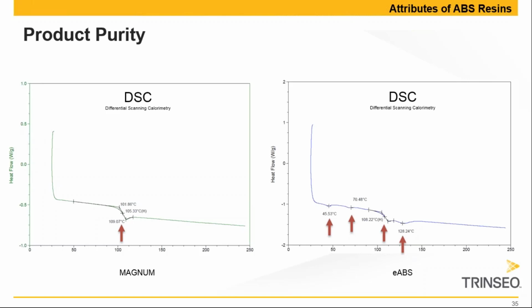I could exclude here one impurity, which is in this case intentionally added. That's the one at 70 degrees. This is a mold release agent, a lubricant that is intentionally added for a specific reason. But the two other 2% impurities, they do not contribute to anything the ABS has to do.